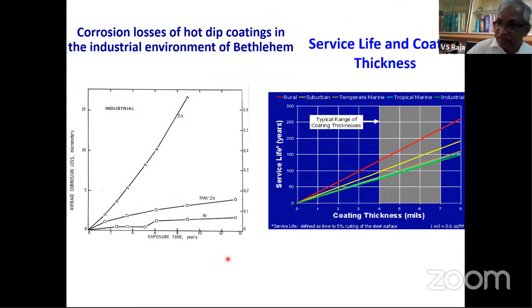One of the important things when we talk about zinc coatings is that the service life of these zinc coatings is related to coating thickness, right? When the coating thickness increases, the service life increases. But look at the steel industry. The steel industry has to increase the thickness by 1 micron. For example, let's take Tata Steel. It has to increase the zinc thickness by 1 micron, spending a few crores, maybe about 20-30 crores annually. They have to spend more money for the same coatings.